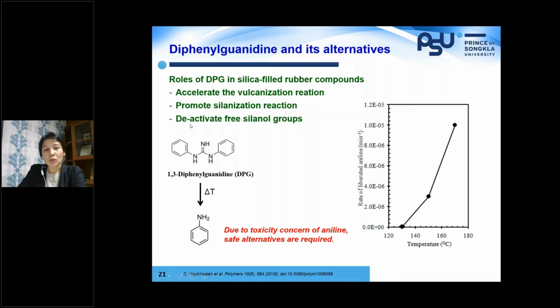And as I said, only about 25% of silanol groups reacted. So we have plenty of free silanol groups. So this DPG can help to deactivate those free silanol groups as well. But the problem is once DPG is decomposed at high temperature, we have aniline, and aniline is a toxic substance. So can we have other additives in replacement for this? If we look at the rate of liberated aniline, we can see an increase of rate already at a temperature of about 130 degrees Celsius, and it increases remarkably at higher temperature. And this range of temperature is the discharge temperature for rubber compound mixing. So if we use DPG, you will have aniline.